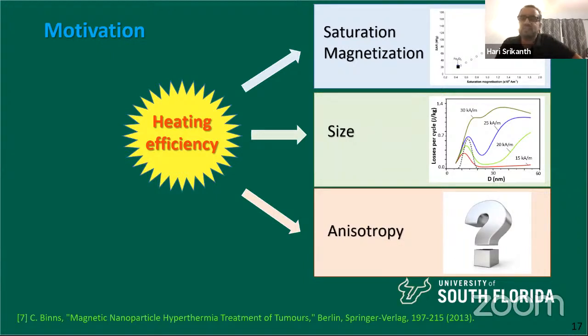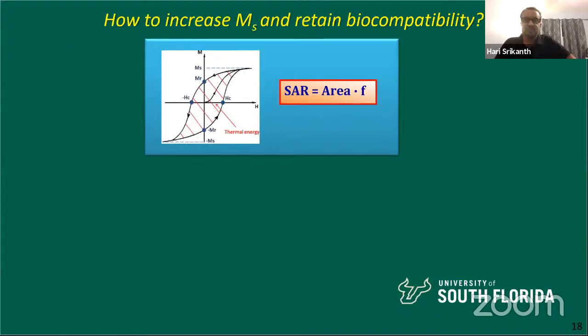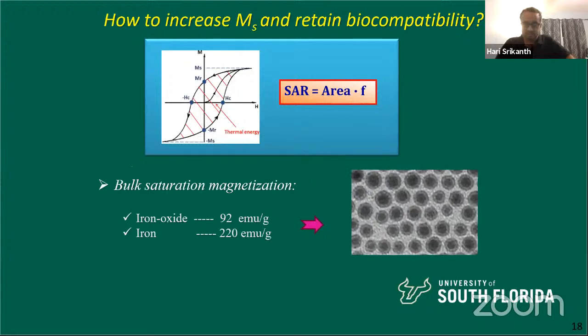But one thing you can see is, can we make a core shell particle where we have the core as iron, which has a larger magnetization, but a thin shell of iron oxide. So we have a core shell system, and essentially, will that improve the SAR? So that's what we tried first. We tried to make core shell particles, and here's a TEM of a core shell particle. Iron oxide is 92 emu per gram. That's the saturation magnetization. Iron is much higher.